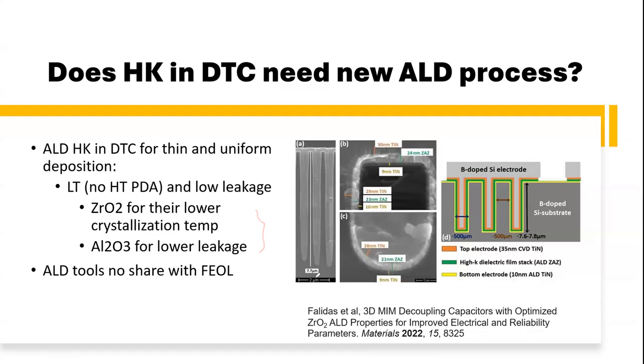These are all good stuff. And I think this is still evolving. That is a 2-year-old paper. But I think people are experimenting with hafnium oxide and aluminum oxide and zirconium oxide with different precursors and trying to eliminate carbon as much as possible because that's a leakage path. Carbon is conductive. Any contamination in your high K creates a conductive path.